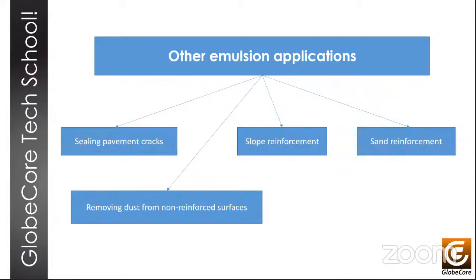Right, so some of the other emulsion applications: crack sealing in road pavement can also be done with emulsions. Cracks are filled with an emulsion mixed with fine-grained sand, leaving a few millimeters to the surface. After settling and solidification, the remaining volume is filled with straight emulsion without sand, and sand is then applied to the surface to protect the patch material from being carried away by traffic wheels. Bituminous emulsion can also be used to reinforce slopes and sands, to prevent dust formation on unreinforced materials, and in many cases emulsions can be used as waterproofing materials.